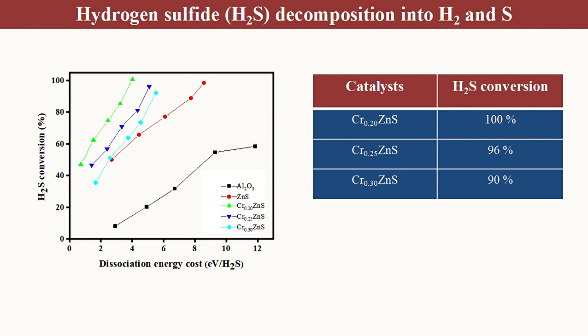All prepared chromium zinc sulfide catalysts showed better performance of hydrogen sulfide conversion than that of pure zinc sulfide and aluminum support. The chromium zinc sulfide catalyst with a molar ratio of 0.20 showed the highest decomposition of hydrogen sulfide. The results after comparison showed that hydrogen sulfide conversion varied for different molar ratios. The catalytic activity greatly depends upon the dopant concentration because it initially increases and then decreases with the dopant content.